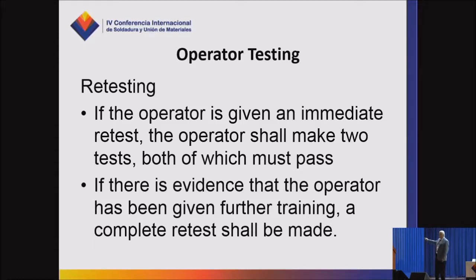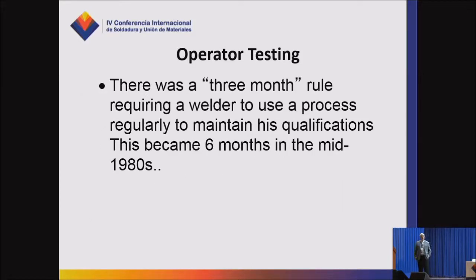Right? If you send him over in the corner and say, go practice over there, learn how to weld a little bit more, and maybe tomorrow when you come back, we'll give you the test again, and maybe tomorrow I won't stand over your shoulder and make you nervous while you're welding your test coupon. Right? So give him more training. He only has to do 1 test. Right? There was a 3-month rule. If a welder didn't use the process every 3 months, he had to retest. That became a 6-month rule in the mid-1980s. So in my early career, when I actually had a job, when I had to deal with welders and make sure they stayed qualified and that kind of stuff, it was every 3 months you had to make sure the welders had welded with the process, and otherwise they'd lose them.